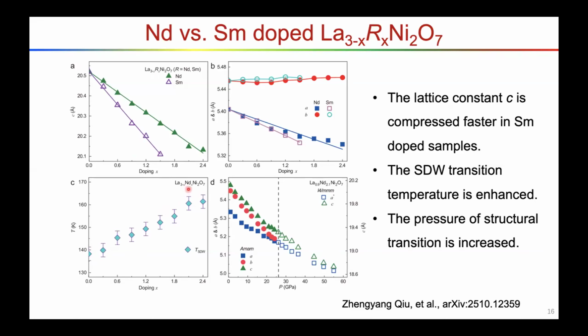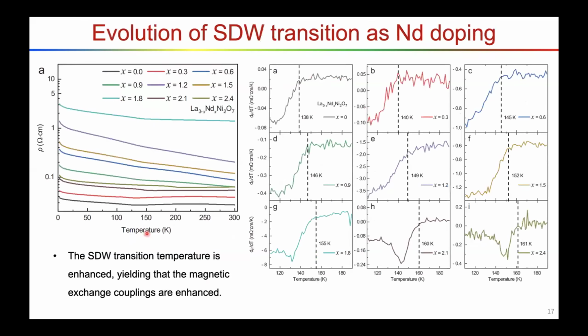density wave transition for the neodymium doped compound is enhanced. For example, as a function of doping, the transition for the spin density wave is enhanced from 140 Kelvin to 160 Kelvin. Those transition temperatures are obtained from the resistance measurements. From the derivative of the resistance measurements, we can see a drop at different temperatures. For example, for 80% doping, the spin density wave transition temperature is at 160 Kelvin. The higher transition temperature for the spin density wave means stronger magnetic exchange couplings.